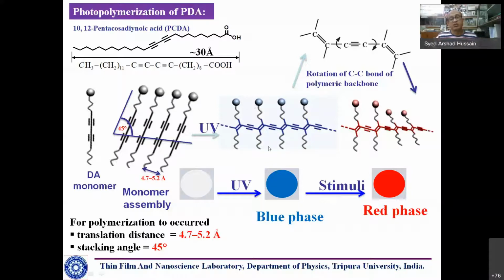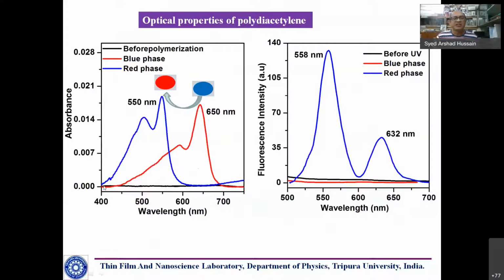An interesting thing is that these two states in polymerized PDA are different. This is blue color, and the spectroscopic feature is also different. And here again, red color. Here also the spectroscopy is different. I show here, you see, this is the monomer. This is a black flat line. When we polymerize with UV, this red color, this is the blue phase. Then if you expose it to some external perturbations, you will see this red phase. Okay, and it's visible with the naked eye. And you see the spectroscopic feature is also different.